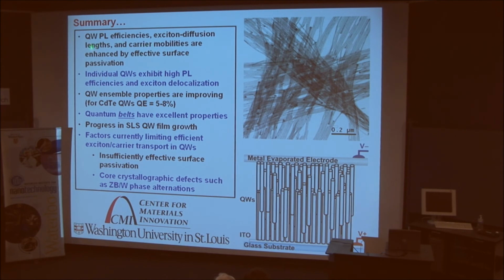The efficiencies and exciton diffusion lengths and carrier mobilities are all enhanced by effective surface passivation. Actually, I didn't prove this today, but we have published some work on this. Individual quantum wires can exhibit high PL efficiencies and show whole wire exciton delocalization. Our ensemble of properties are improving. So, for example, with the cadmium telluride quantum wires, we're now up to about 5 to 8%. Quantum belts seem to have excellent properties. We're making some progress on SLS quantum wire film growth.